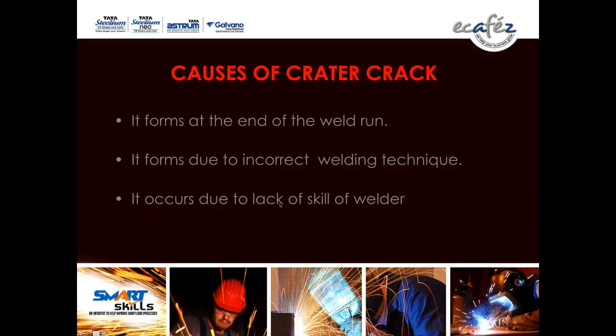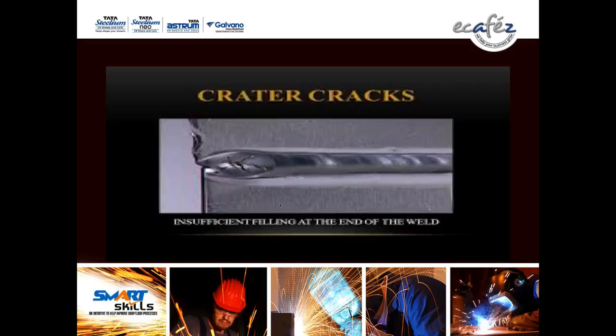Causes of crater crack: it forms at the end of the weld run. It forms due to incorrect welding technique. It occurs due to the lack of skill of the welder. See the pictorial view of crater cracks, which occur at the end of the weld. This is due to insufficient weld filling.